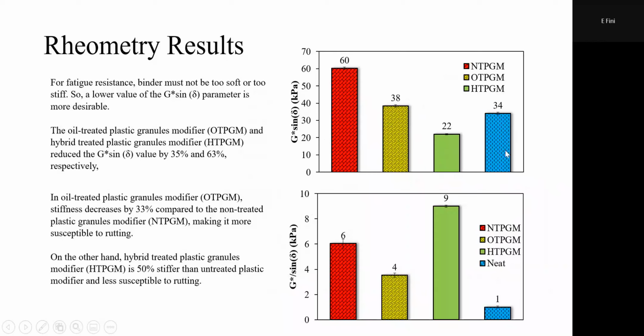Interestingly enough, the 34 is just asphalt. And you can see that when you add plastic, your fatigue will jump so high. So it doesn't mean that by adding plastic just as is, without compatibilizing them, you're doing a good thing, because the fatigue could be just lost. And now you're having a material that can be very prone to cracking, fatigue cracking.